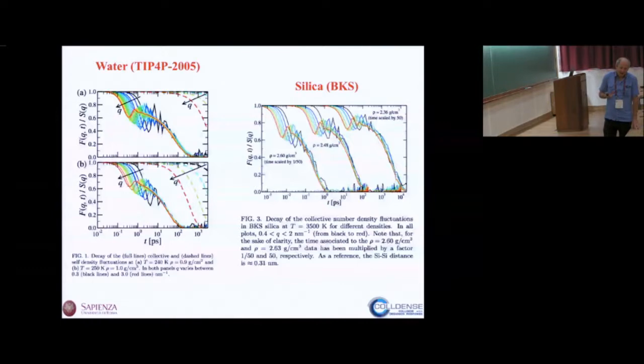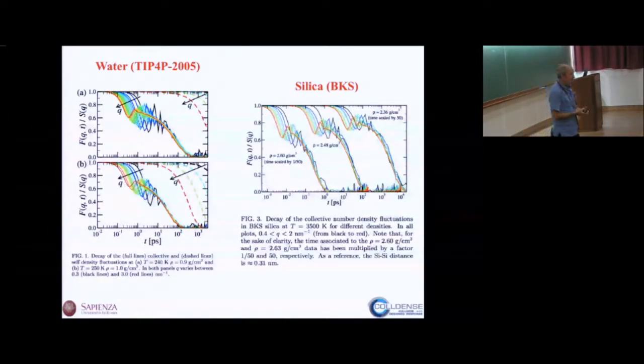I like to explain this very quickly by saying that we always have to remember that density is a ratio between number of particles and volume. And so if you cannot decorrelate by changing the number of particles, you better decorrelate by changing the volume. And indeed, this is what is happening. Those are decorrelations associated with the propagation of the normal modes of the system: the oscillations in the system, elasticity fluctuations that propagate through the system and decorrelate the correlation functions.